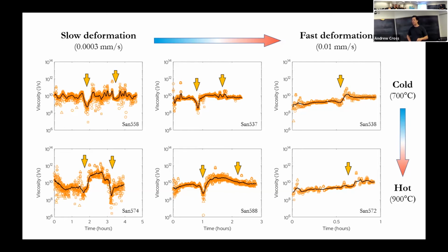We don't really see too much of a viscosity drop, or rather, we see the most dramatic viscosity drop during the up-pressure transformation. So that's going from quartz to coesite. As we go back down through, we don't really see too much of a drop off in viscosity. And then once we go to our fast deformation rate, we maybe see a tiny little blip, a little decrease in viscosity. But really, there's not much of an effect there in terms of sample strength.